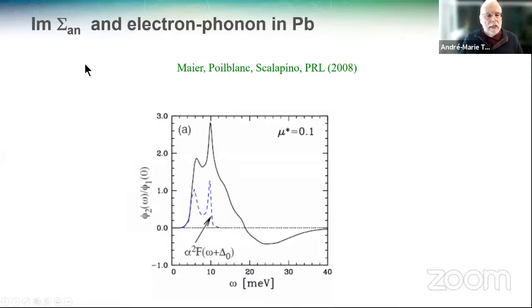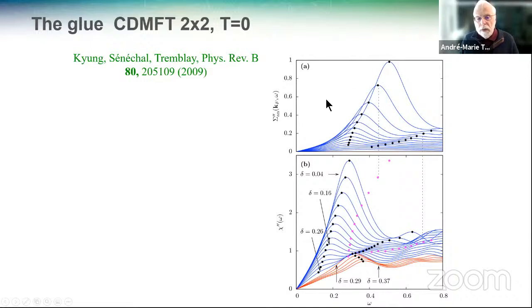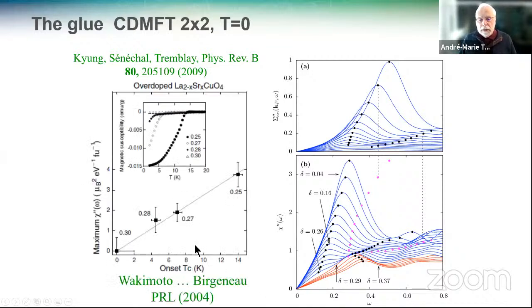So what is the glue? In the electron-phonon case, just Eliashberg or BCS superconductivity, there are two peaks in the imaginary part of the self-energy that are related to peaks in the phonon spectrum. So this is frequency and this is the imaginary part. Here we can do the same, and we look at the imaginary part of the anomalous self-energy. There are two peaks, and we look at the imaginary part of the local spin susceptibility, and you see that the peaks, if we translate this down here, match.